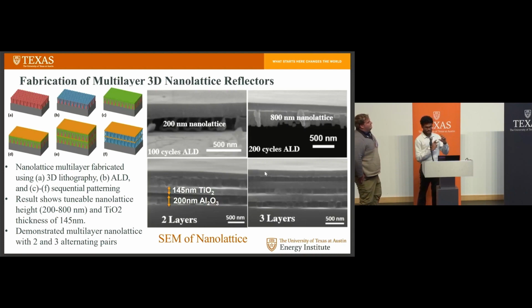So you can see there are two layers now, one a porous aluminum oxide lattice and a solid layer of titanium oxide lattice. These two have different refractive indices. The porous aluminum oxide has an index of about 1.06, and the titanium oxide has an index of 2.7. So this high refractive index mismatch will lead to really high reflectivity across a broadband spectrum. We can keep repeating these processes in order to stack multiple pairs of aluminum oxide and titanium oxide on top of each other, and finally remove the resist in order to reveal the porous nanolattices. On the right-hand side, you can see some SEM images of the samples that we have fabricated,